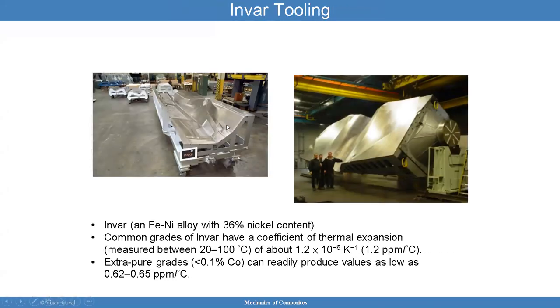Here's an example of an Invar tool. Invar has a lower coefficient of thermal expansion, which makes it a good application for draping composites. Here you can see a high performance part, tooling. High performance tooling is expensive. Invar is a very expensive material. It has 36% nickel content, and there are various common grades of Invar, but the point is that the thermal expansion is fairly low. You can look at other grades as well.